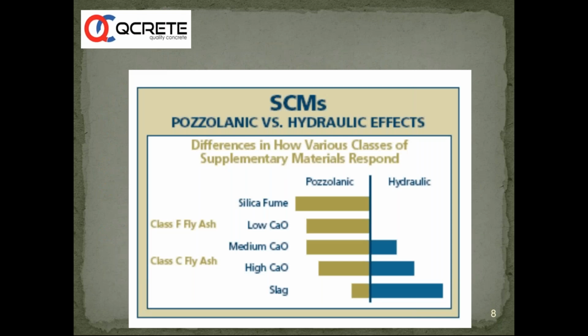When we are talking about SCMs, we need to think about how it reacts with cement plus water, whether it is pozzolanic or hydraulic. Hydraulic means it reacts with water easily, and here you can see when the fly ash has high CaO, some fly ashes may have a CaO content of 20%, 30%, things like that. In that case, it will become hydraulic in nature, and you can see GGBS also is comparable, and it is going into the hydraulic region, whereas other materials which are predominantly having SiO2, Al2O3 plus Fe2O3 come under the pozzolanic classification.